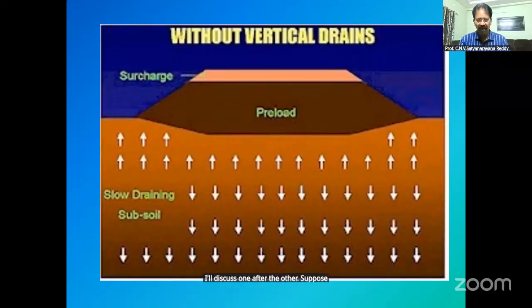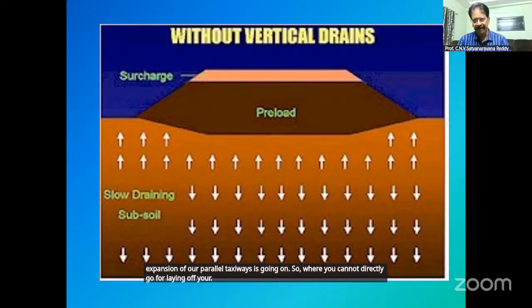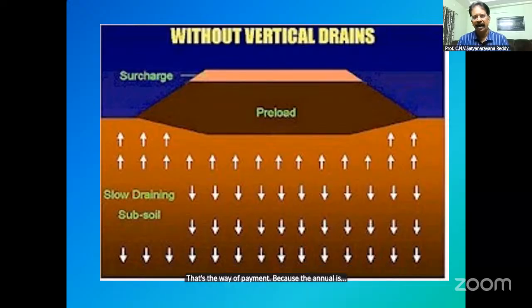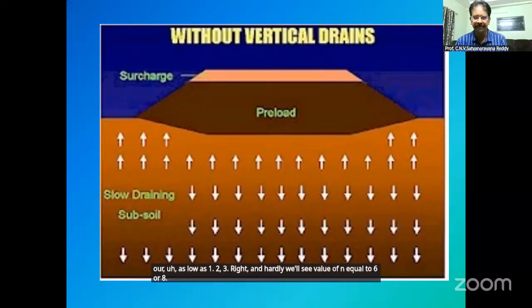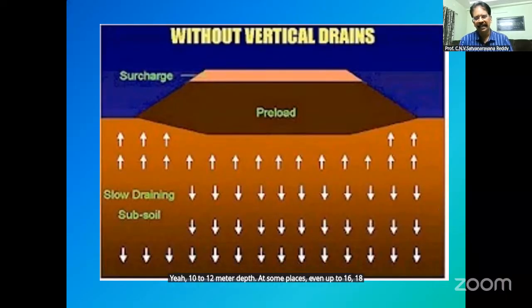Suppose I have a soft clay deposit and I want to construct a facility there. For example, you can take Visakhapatnam airport. There you have thick deposits of soft clay extending to 14 to 18 meters depth. At present, expansion work for parallel taxiways is going on. There you cannot directly go for laying of your taxiway pavement, because the N values of the existing clay are as low as 1, 2, 3. Hardly will we see a value of N equal to 6 or 8 at 10 to 12 meter depth. At some places, even up to 16, 18 meters, N values are only 3 and 4. So without strengthening such soft clay, you cannot lay your pavement there.